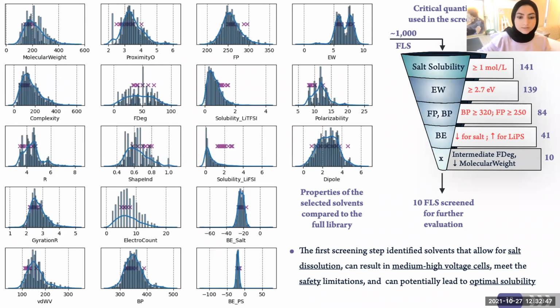And from these 141, we identified 139 solvents that meet the electrochemical window greater than 2.7 electron volt. Out of these 139, we found 84 that meet the safety considerations of boiling point and flash point. And from the 84, we found 41 that have lower solubility towards the polysulfides than the conventional glymes, but with a comparable affinity towards the salt, because we don't want to compromise the salt solubility significantly. And this step is based on the binding energy DFT calculations. And finally, out of the 40 or 41 solvents, we down-selected around 10 that have intermediate or low intermediate fluorination degree and low molecular weight, or commercial availability, for further evaluation.